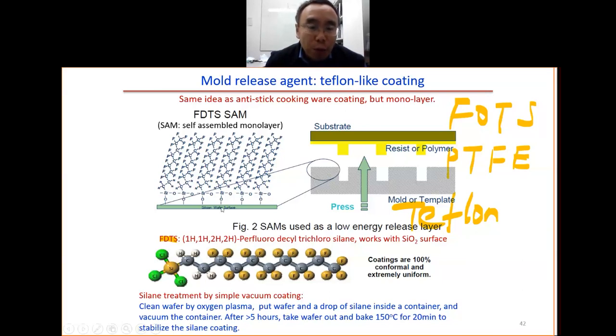On the other side, we have this chemical bond. When we have chemical bond, it will be very stable on the wafer surface. So how to do this process? So this molecule gives you this kind of coating. It's a self-assembled monolayer. How does this thing work? So here we have this trichlorosilane. So we have this thing. We look at this group here.